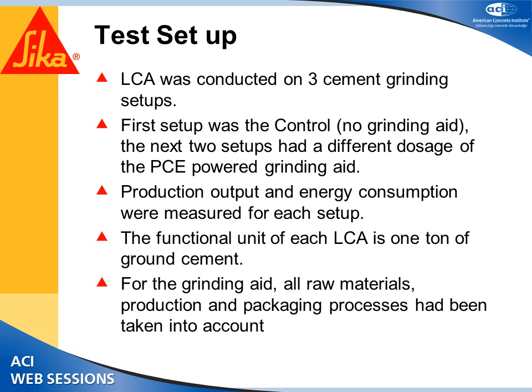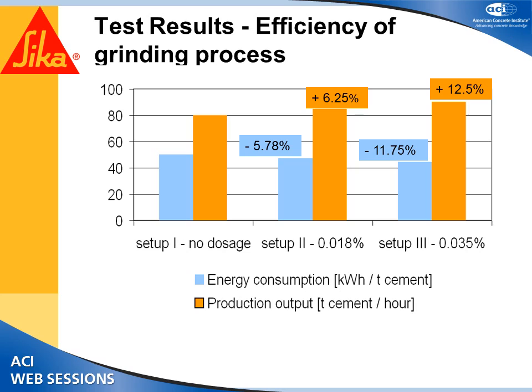So moving on to the test setup for the grinding aids testing, the LCA was performed on 3 setups. One was a control, no grinding aids, and the 2 were with grinding aids, one at a lower dosage, one at a higher dosage. The production output and energy consumption were measured for each setup. The functional unit was 1 ton of ground cement. And for the grinding aid testing, all the raw materials, production and packaging process have been considered. So this was the result.